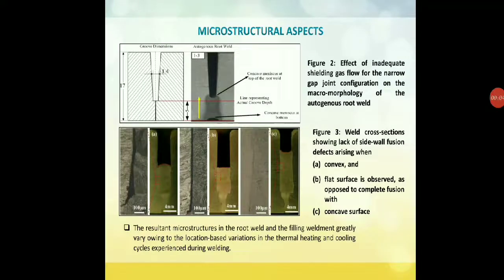Yeah, if I talk about the microstructural characteristics of NGLW joints, this processing technique is almost related to the laser cladding process. The product obtained from the NGLW process is subjected to high cooling rates of almost around 400 degrees Celsius per second. So, therefore, the microstructures in the root weld and the filling weldment greatly vary.